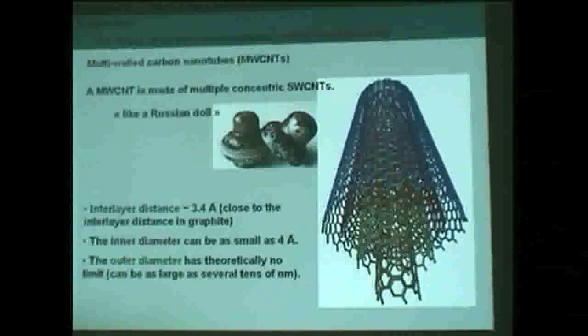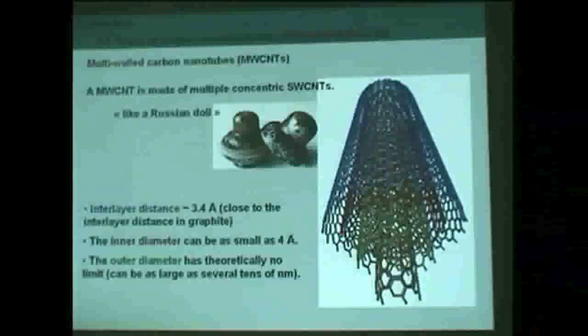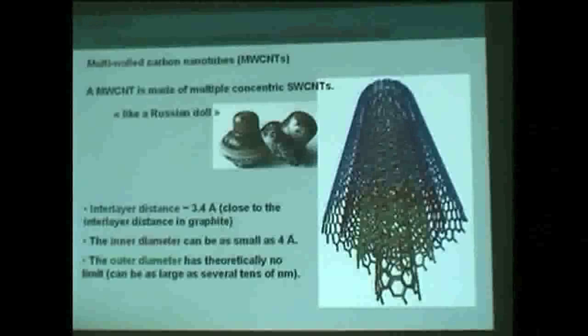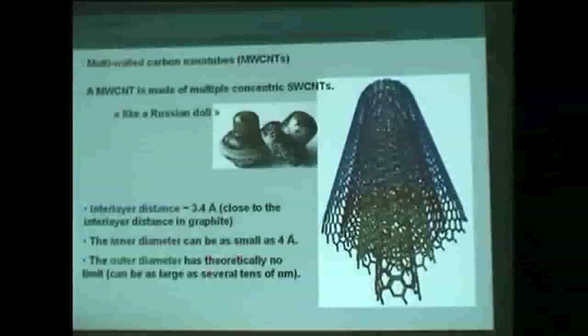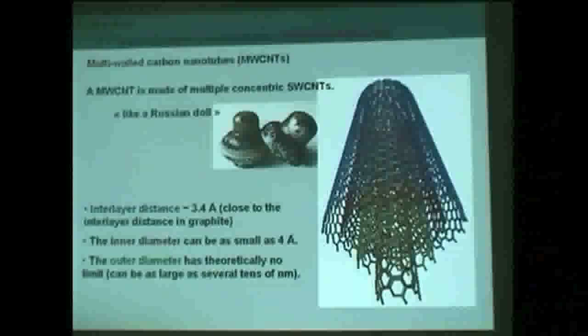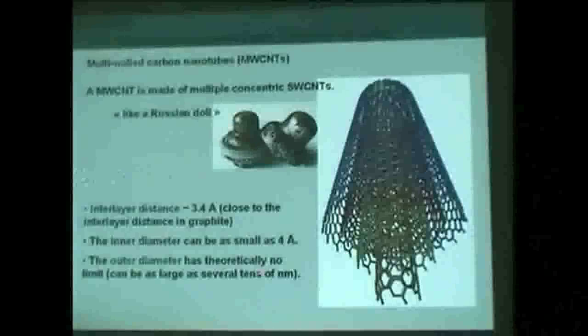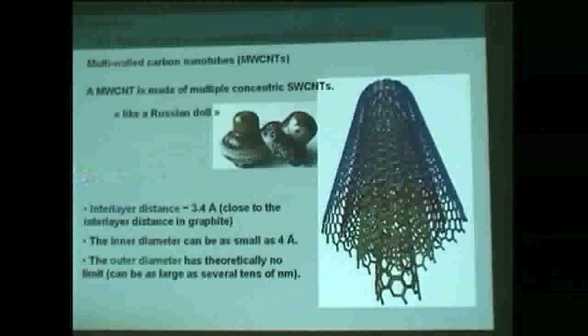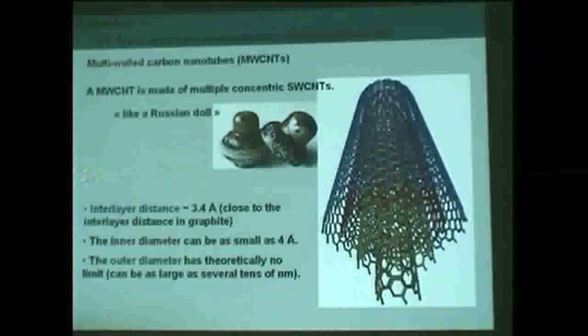The outer diameter can be very, very large because in this case, the outer tube cannot collapse thanks to stabilization by the inner tubes. It prevents collapsing because these tubes are much more rigid, not flexible like single wall tubes. The outer diameter can be very large - there is no theoretical limit. Experimentally, it can be as large as several tens of nanometers, or 100 to 150 nanometers.